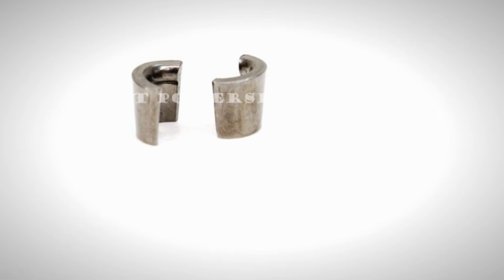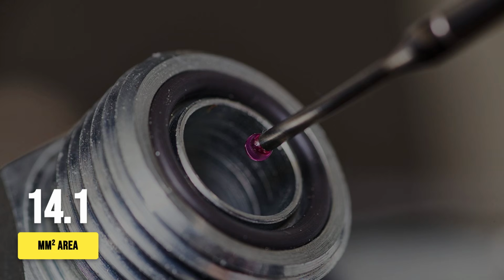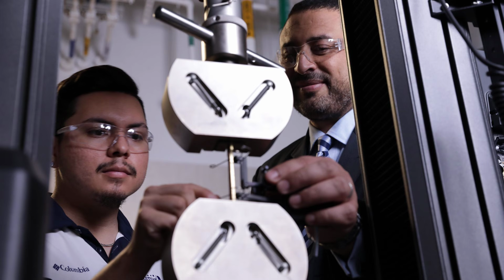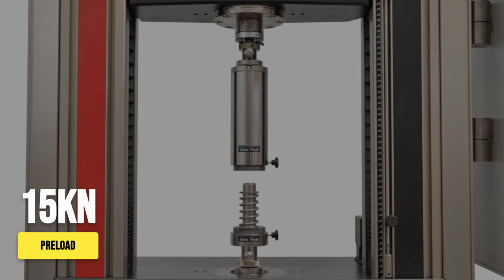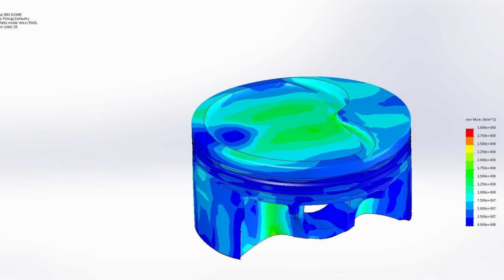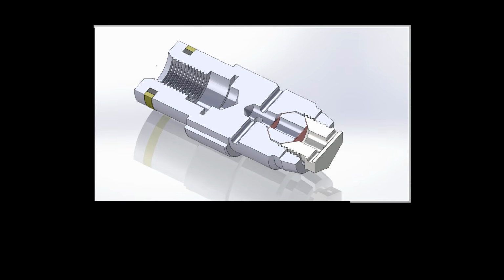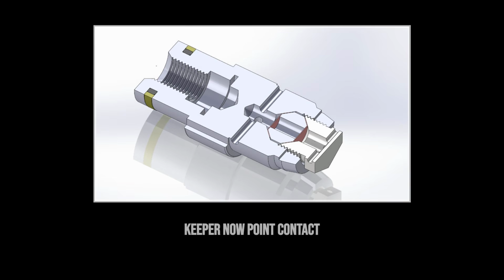Contact area math is not theoretical. The OEM keeper, at 2.00 millimeters, provides a bearing area of 14.1 square millimeters. The aftermarket unit, at 1.91 millimeters, drops to 12.7 square millimeters. Under a spring preload of 15 kilonewtons, the local pressure spikes from 1060 to 1180 megapascals. The safety margin vanishes. The keeper is now a point contact, not a clamping surface.